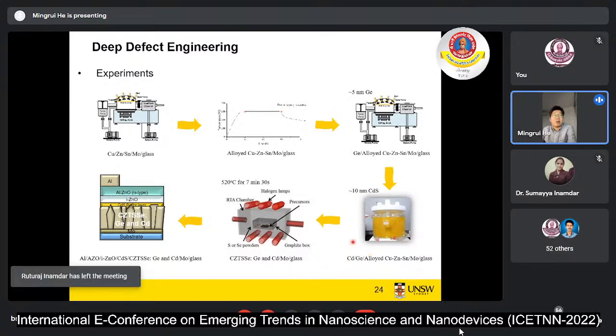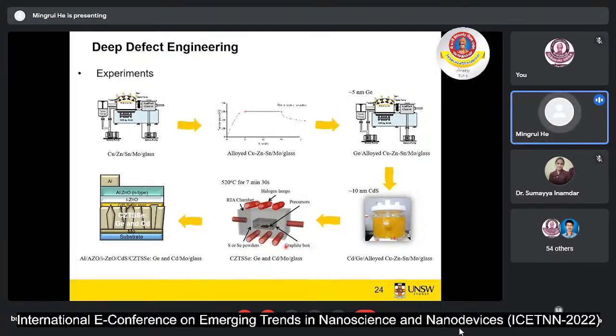After that, this precursor will undergo sulfur selenization at high temperature within a sulfur and selenium atmosphere. After that, I get the CZTSSe absorber with germanium doping and cadmium alloying. Then I followed the procedure for the CdS window layer and the metal contact.